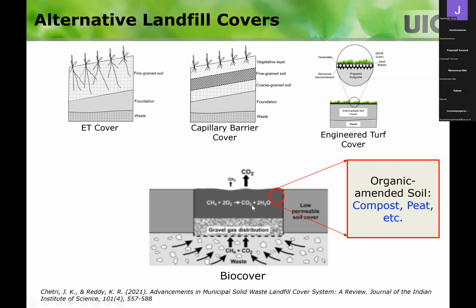Now, these materials that you see, compost and peat, they are not stable materials. So if a compost is not matured enough, the degradation of that will generate methane, more methane. So when you add compost into the soil and they put this one, you're creating more methane. And they could degrade with time.